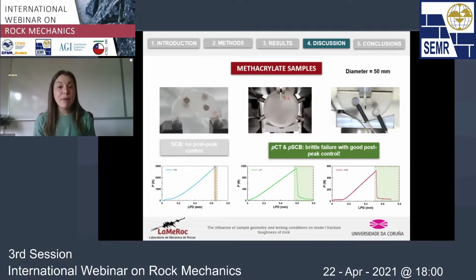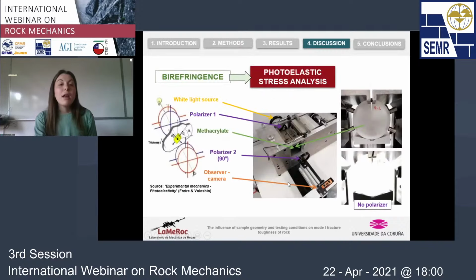We have used, in this case, methacrylate, and we have performed the three experiments using these three testing approaches. And we could see that, as happened in the case of rock, we had no control on the SCB, but in the case of the PCT and PSCB, although we observed that the failure was really brittle, we still had some control on the propagation of the cracks. But using methacrylate had also a second intention behind. Methacrylate has a very useful property, which is called birefringence. So thanks to this property, we could perform a photoelastic stress analysis of the sample using this simple testing setup.